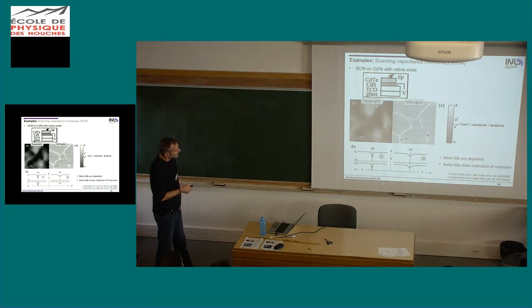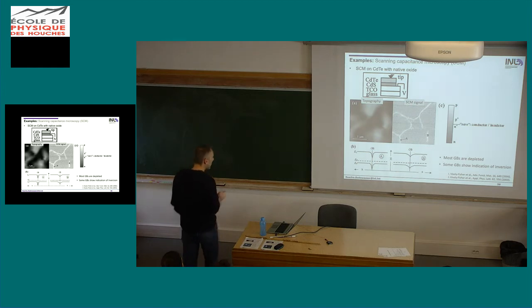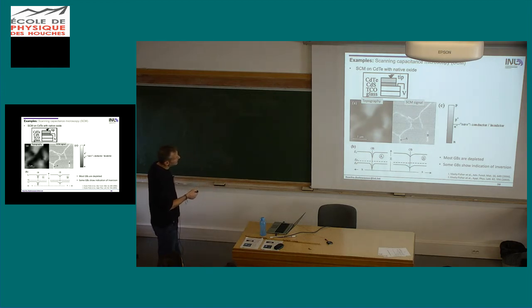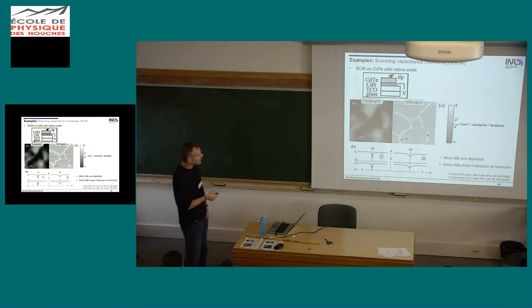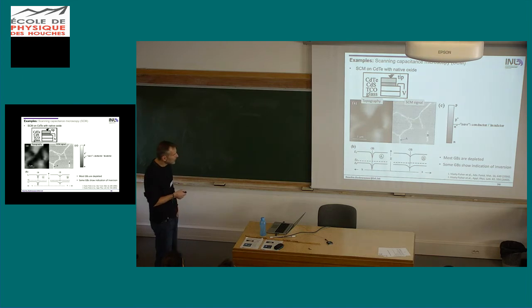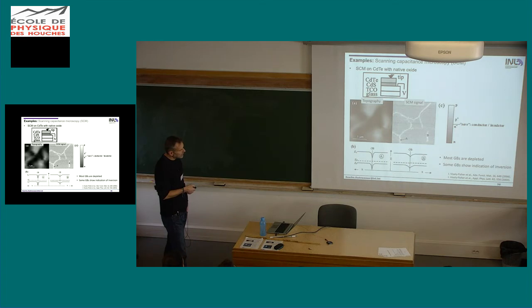And then in the topography, you see these grains. The image quality is not so nice here. Anyway, what you see in the SCM signal, you see these white lines at the position of the grain boundaries. And the color coding here is that white would mean lower doping, and the darker would mean higher p-type doping. So what they explained is that at these grain boundaries there's a band bending. So it's a downward band bending, it's a p-type material, and this means in the grain boundary I have essentially a lower doping. My Fermi level is further away from the valence band in this case.